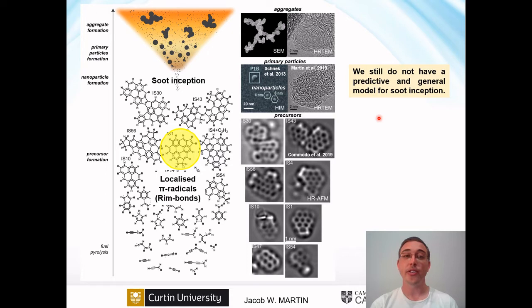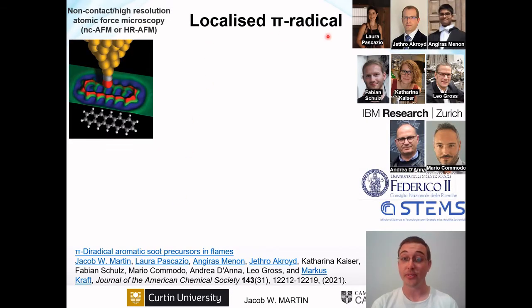So in this talk, I'm going to be talking about two reactive species and why we're quite interested in them as a potential pathway to how soot forms. The first thing is these localized pi radicals. This work was done in collaboration with IBM Research and also with Dr. Andrea D'Anna and Dr. Mario Commodo from Italy. In this work, molecules from the flame were extracted and then were imaged directly with non-contact atomic force microscopy. And this is really quite neat. Using a functionalized tip with carbon monoxide here being the functionalization molecule, you're able to tactile, so you're able to feel the molecules and actually see the bonding network, which is really remarkable.